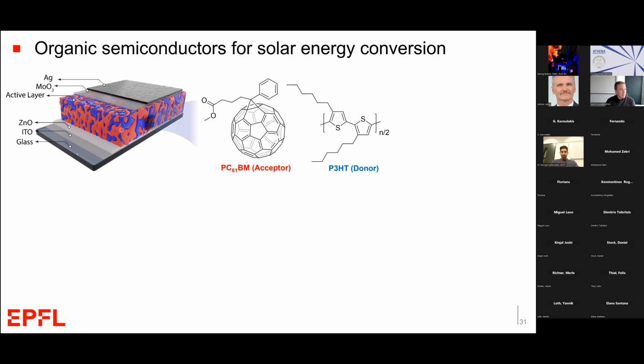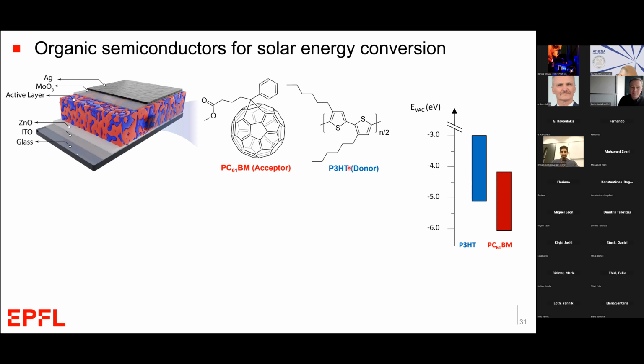And the intimate contact between the donor and acceptor is necessary because upon light generation, for example, in this P3HT semiconducting polymer, a free electron and hole is not produced. Given the optoelectronic properties or the electrostatic nature of these materials, we produce a bound electron-hole pair or an exciton. And only when that exciton can reach an interface with an electron-accepting material like this fullerene can we separate charges into the free electron and hole pair. And because the exciton diffusion length is only on the order of 10 or 20 nanometers, this intimate contact between the two phases of the donor and the acceptor needs to be on that length scale.